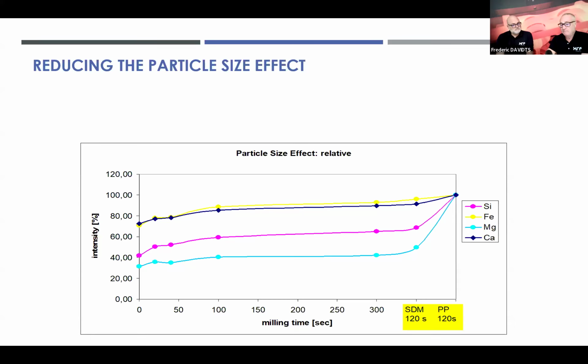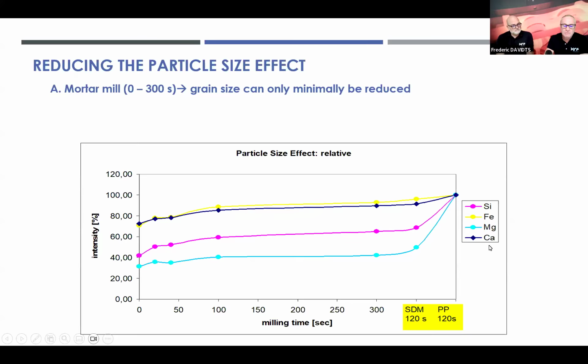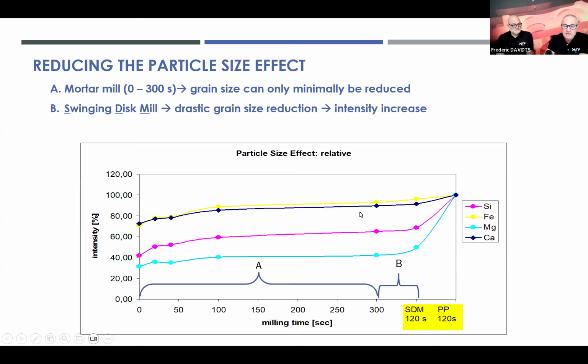So I've done three tests here. The first one is that I have done milling of one and the same sample. If I remember well, it was a clinker sample. I first did not grind it, so 0 seconds, and then I ground it up to 300 seconds. We can really see for all the elements, silicon, iron, magnesium, and calcium, just a very slight intensity increase. And as soon as I grind the sample with a swinging disc mill, we can see the intensity going up.